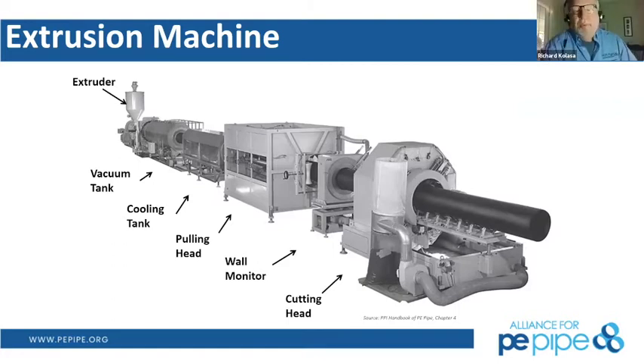The reason we have to put it under vacuum is because if we didn't, gravity would just pull that molten material down, and it would fall, and you would end up with a big U shape. Then you continue to cool it, and then you have the pulling head that literally pulls the polymer from the extrusion die head. You have a wall monitoring system, so you monitor the complete line of the products made, and then you have the saws that cut it into the appropriate lengths that you require. Next slide, please.